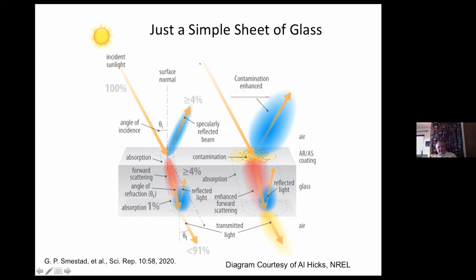The situation becomes much more complicated when you have the contamination. The transmitted light that I showed you in those previous plots, that's this term. That's what's left over. What is altered is the reflection and the absorption. So this is clean and dirty. AR is the anti-reflection or an anti-soiling coating, which can change and make this situation more complex itself.